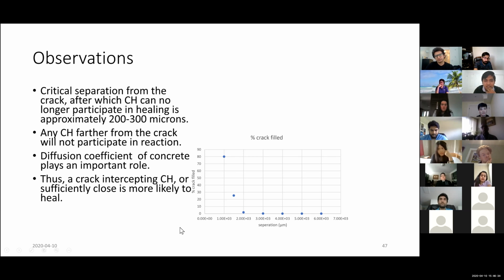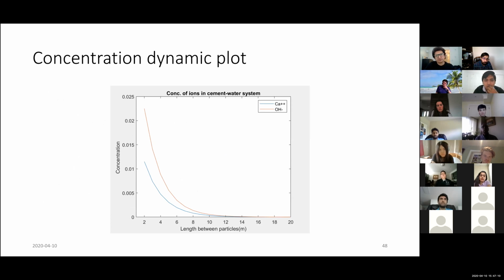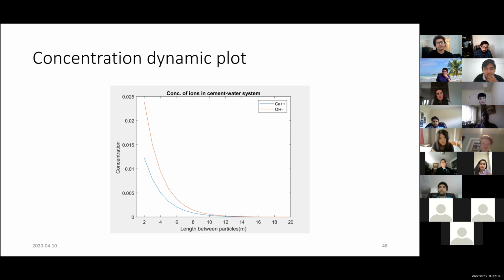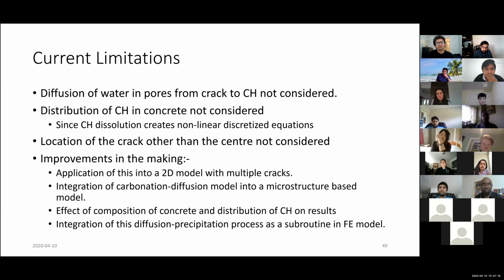So there is a decrease in supply of calcium ions from a distance towards healing of a crack. If we can calculate the diffusion coefficient of concrete, we can put it into this model for calibration, and in one dimension this shows how much it has contributed. If I do this in a microstructure based system, I can see how much calcium ion each crack or each void can get from outside. This is just a plot of calcium and hydroxide ion within the system.